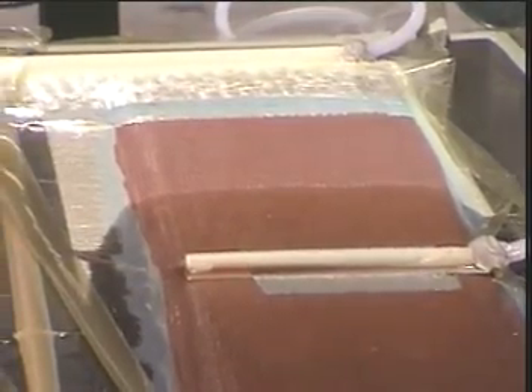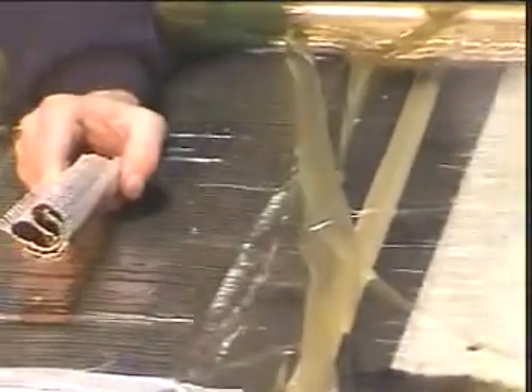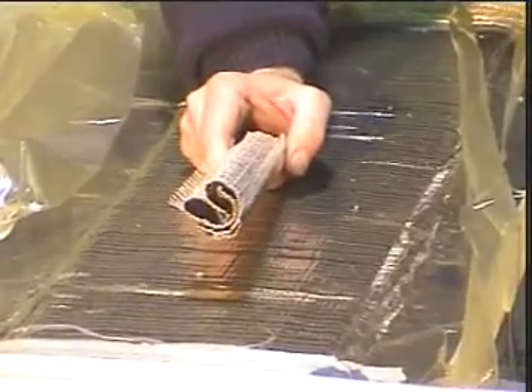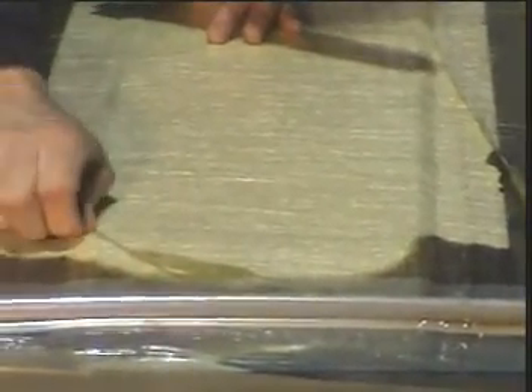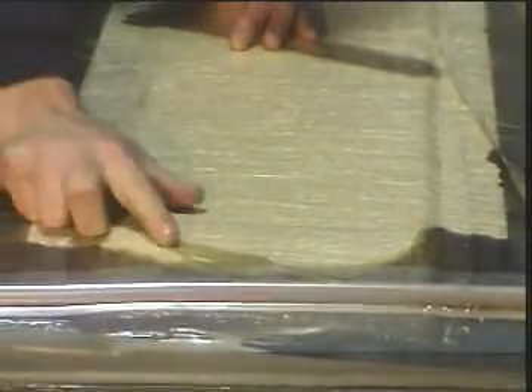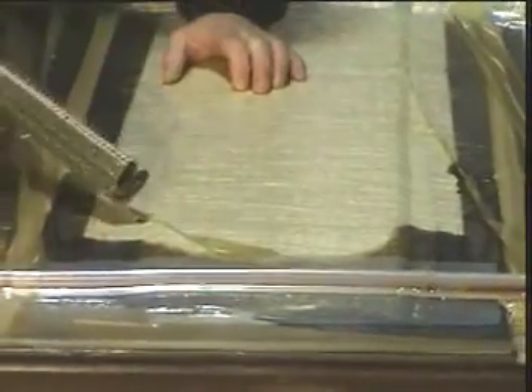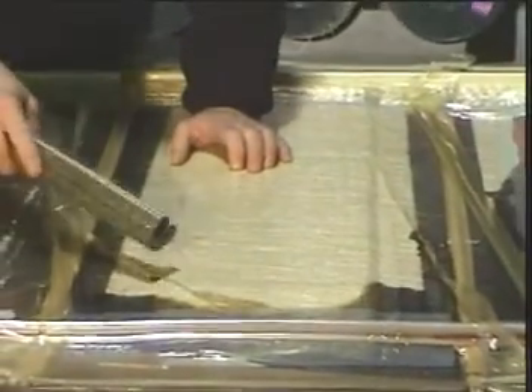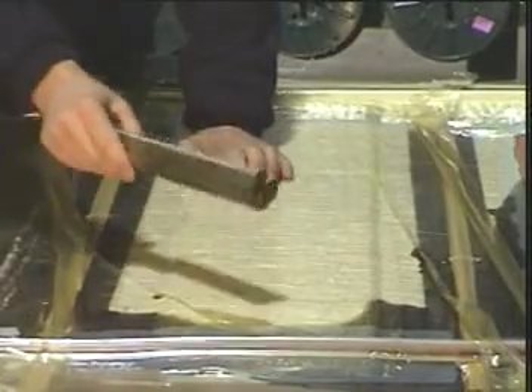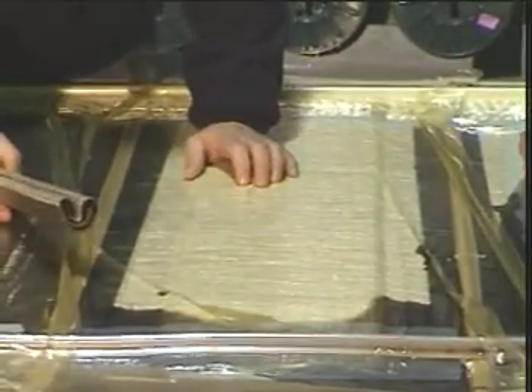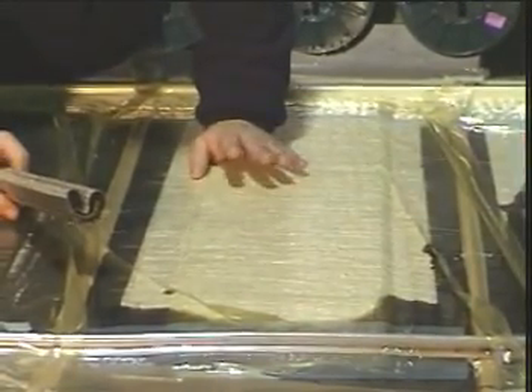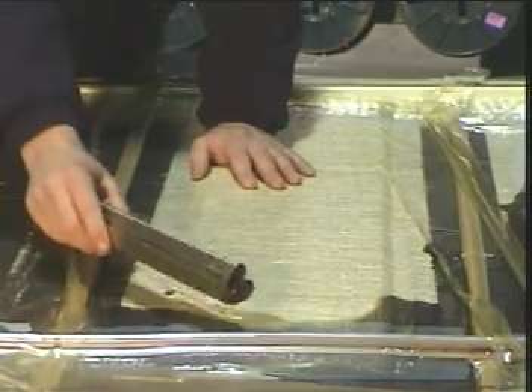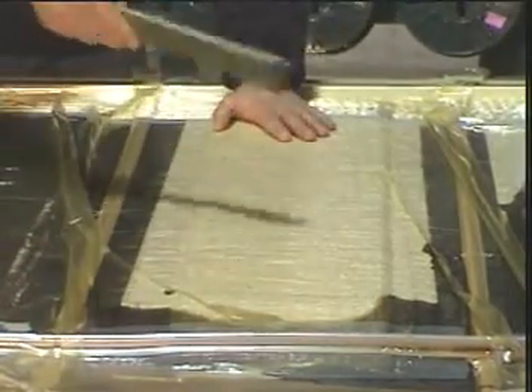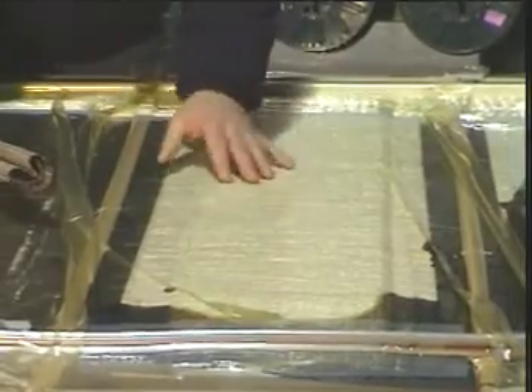These other panels, though, really show things going horribly astray. You can see the difference, the glass is wetting out some. We're getting more wet out because of the wrinkle in the bag actually transferring some of the resin. You can see it kind of gurgling through there. Again, creating a dry spot here. That would really be a problem in a large part. That would be causing you enormous problems. And you can imagine the gel time to get the resin from here to here, it would take days. There's no way it would get there.